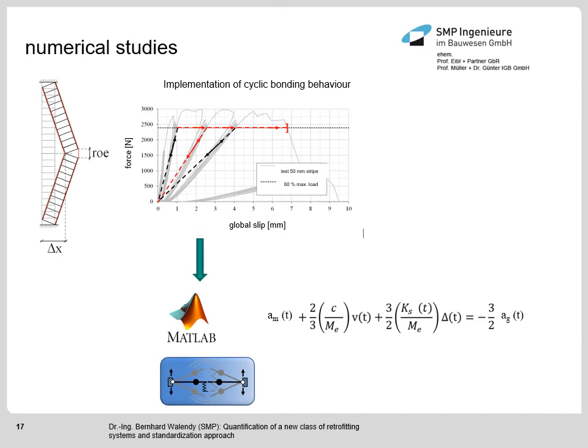and the material behavior which is implemented links the crack opening to a transferred tensile force within the retrofitting system. And for this material behavior, an ideal linear elastic plastic material behavior is implemented, but we have a completely damaged system, which means after reaching the plastic plateau, there is no additional energy dissipation, which means we have completely closed hysteresis.